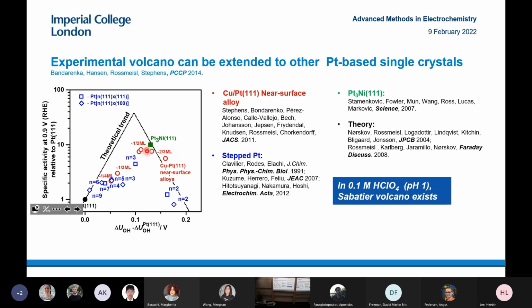So we think that this is pretty good experimental proof that this oxygen reduction volcano exists. We're very excited about this, and it's also much more direct than other proofs in the literature, because we're actually measuring the OH binding energy on a very well-defined surface, and also measuring the activity on the same surface.